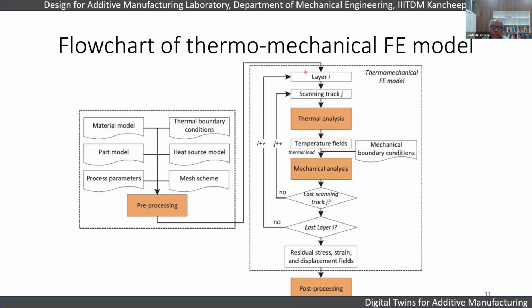You do the pre-processing. For each layer, you iterate, layer 1 to layer 10, depending upon the number of layers in the part. For each layer, you iterate over each scanning track, do the thermal analysis, get the temperature field, apply the mechanical boundary condition, do the mechanical analysis. And when that laser scanning track is done, you go to the next track and do it again. So you iterate until all the tracks for a particular layer are done, and then iterate for all the layers.